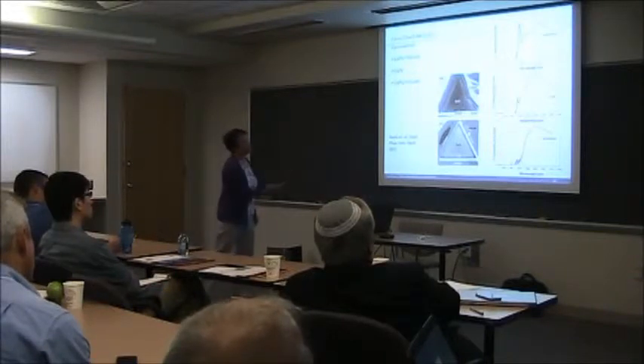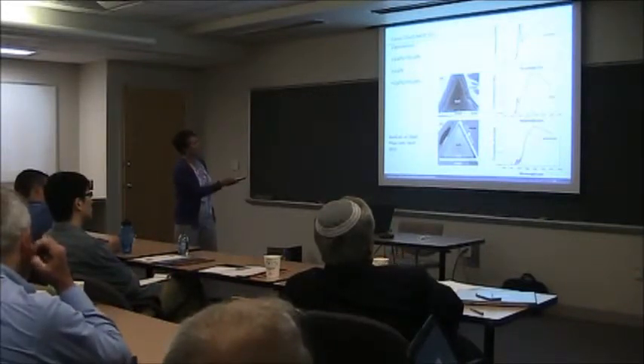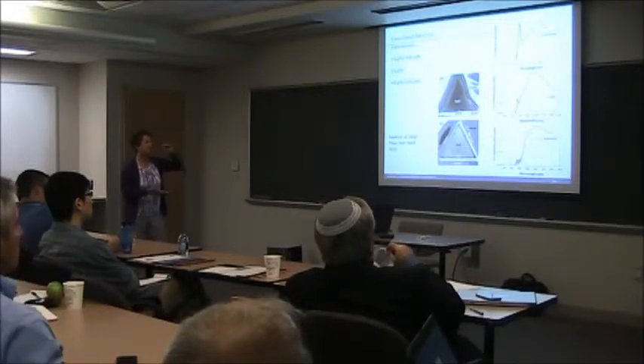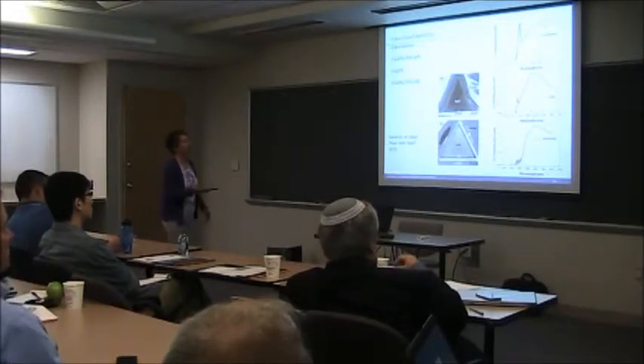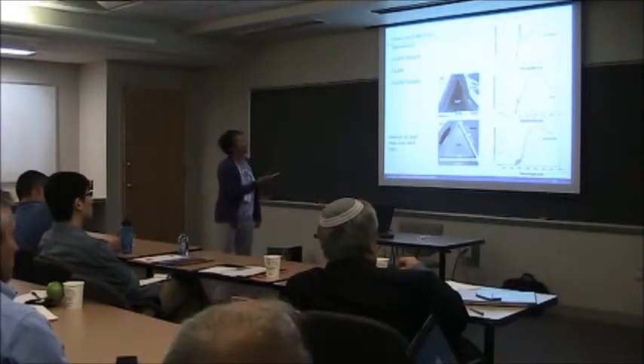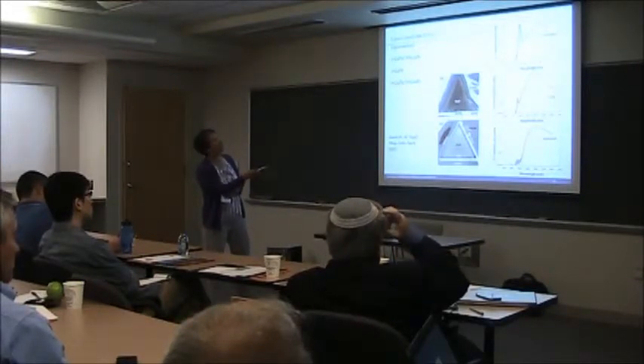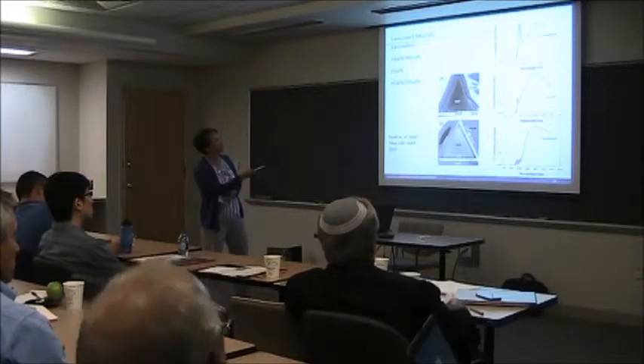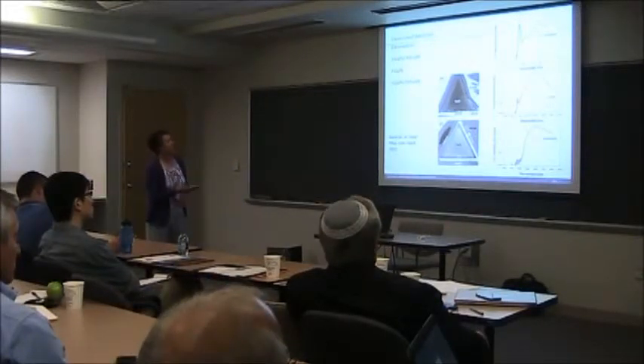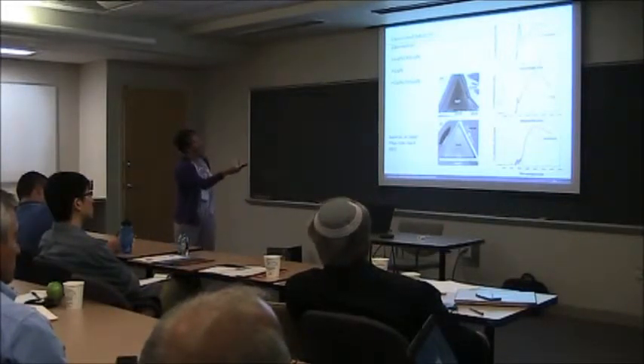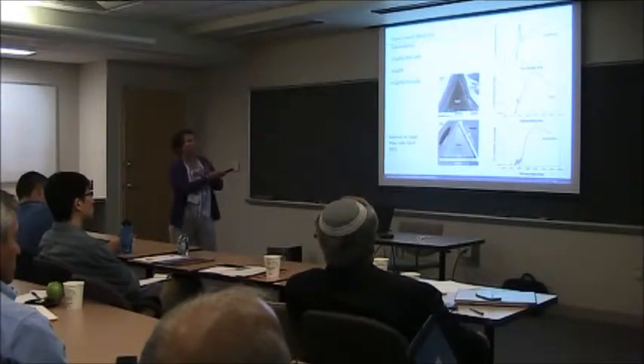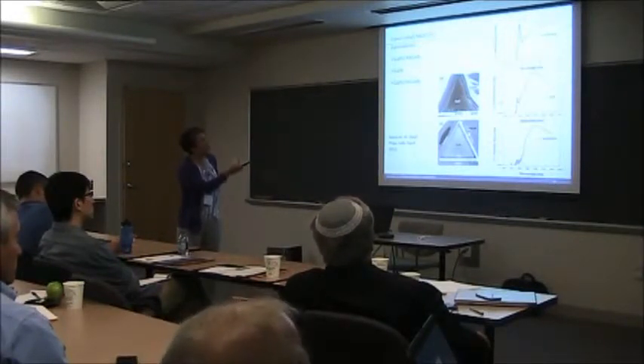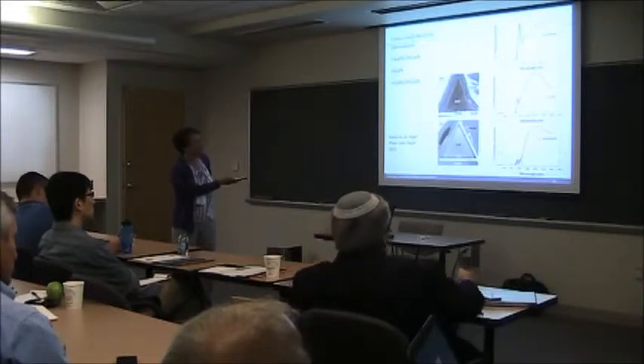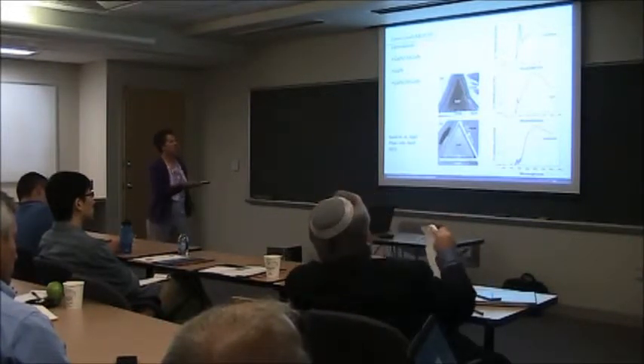So indium gallium nitride has a smaller band gap. Aluminum gallium nitride has a bigger band gap. It should be more like a traditional heterostructure, and then the bare wire. Okay? If you do standard CL, these are the spectra that you see, and they're on log scales, just so you get a sense. But here's the near edge peak, and you notice, not too surprisingly, that when you have a nicer heterostructure, you get a pretty decent near edge peak. Still visible for an uncoated one, but much weaker. And then with the InGaN there, almost like a surface sink, right?